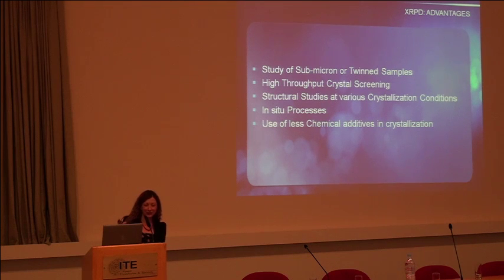I'm interested in in situ processes, chemical reactions. And we believe that the technique is ideal also for capturing diffraction data at very short time frames in order to follow a chemical reaction or a structural evolution upon variation of a physicochemical environmental condition, for example humidity. And we usually use fewer chemical additives, because to prepare this precipitate, which is a very bad sample, you don't need to introduce many crystallization agents in most of the cases we've seen to date, at least.